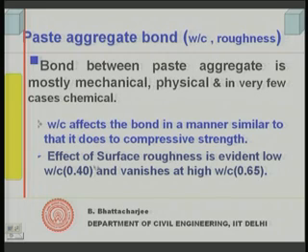So, this test is really difficult, but some tests were done earlier and it was observed that aggregate with higher surface roughness can increase the strength at low water cement ratio, as much as about 38% increase in some cases. However, as the water cement ratio increases, this increase in strength due to surface roughness tends to reduce, and at about 0.65 there is no increase, because the water cement ratio becomes so governing that whether you have a rough surface or a smooth surface, it really does not make much of a difference. But at low water cement ratio this has some effect.